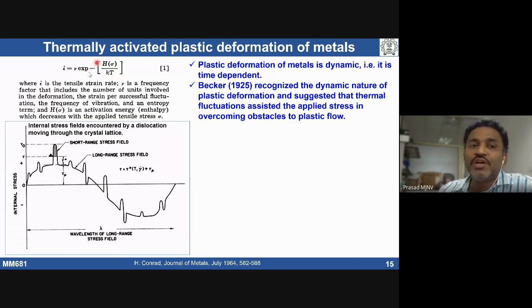Look at here, this H of sigma decreases with the applied stress. Typically, the activation energy is going to come down with increasing applied tensile stress. So the thermal barriers, which can be overcome by thermal fluctuations, can assist the deformation very easily. That process is called thermally activated plastic deformation of metals.